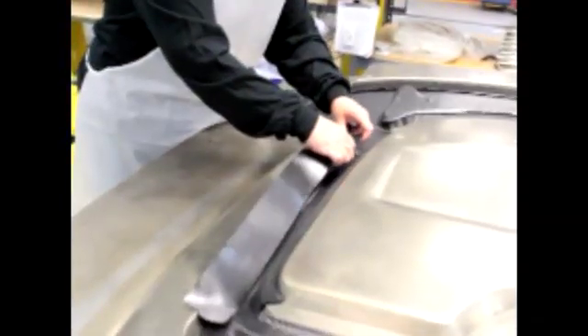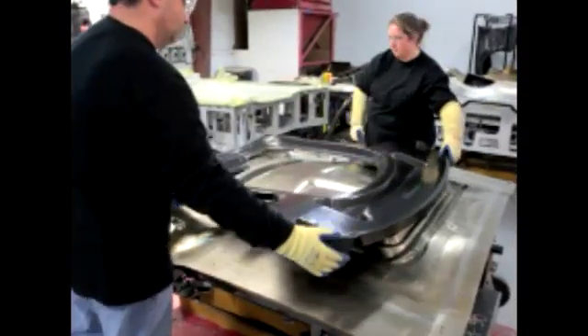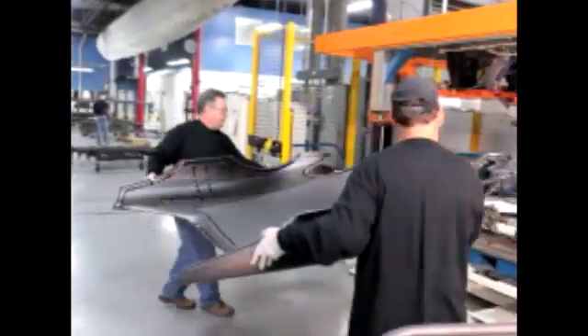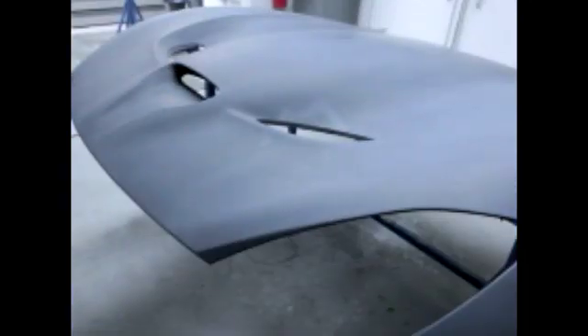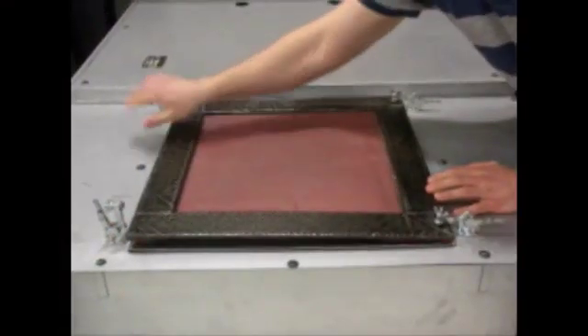It is, because of the complexity of the parts, the size, the sheer magnitude of the clamshell hood, and the complexity of a structural roof in carbon fiber drove it to the more conventional technologies. But at the same time, we're doing everything we can at Plasan to drive out the processing costs. Some of the manual processes we're automating. At the same time as launching the Viper, we validated and are in the process of commercializing a new process for forming carbon fiber, which basically takes the cycle time down from 90 minutes to 17 minutes.